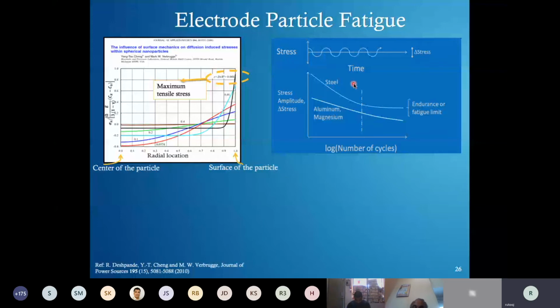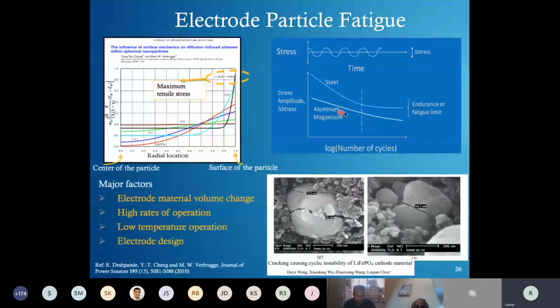And if you go to fatigue mechanics, every material can sustain a certain stress for so many number of cycles. So this is basically the number of cycles to failure for a given stress, which you can know from fatigue mechanics. Similar principles could be applied to electrode particles, and we can know basically how much stress the electrode particle is suffering, and what it means to the particle. So the higher the rate, the higher the stresses would be. At lower temperature, again diffusion becomes slower, and then the stresses become higher.